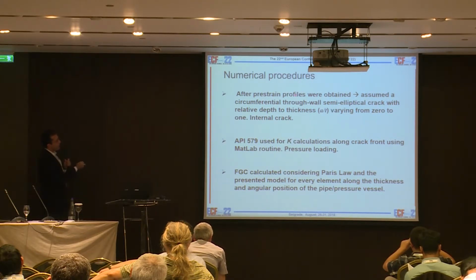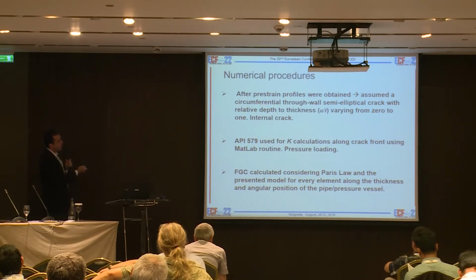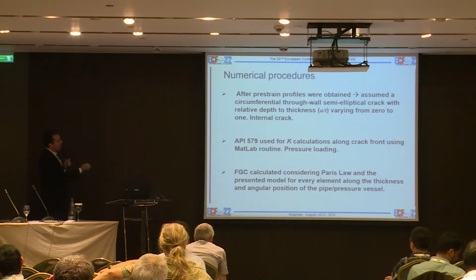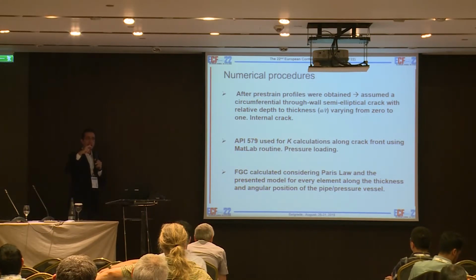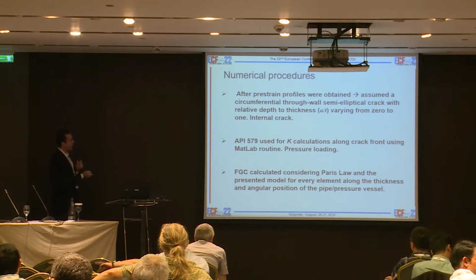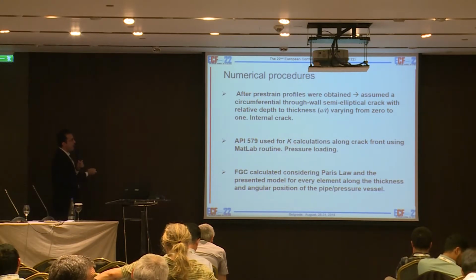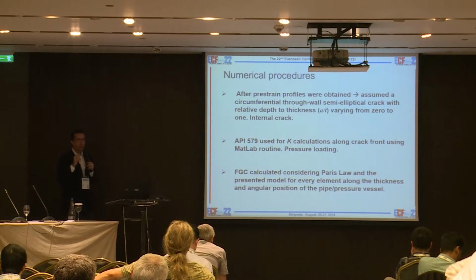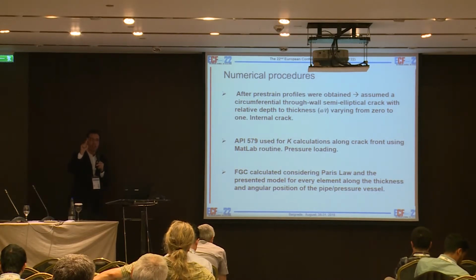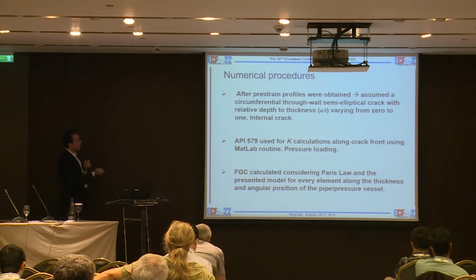After we simulated and got the pre-strain profiles, we assumed a circumferential through-wall semi-elliptical internal crack, with relative depth A/T ranging from 0 to 1. So the crack started inside and it grew until it reached the outside part of the pipe. API 579 was used for the K calculations, and a MATLAB routine was used to calculate K along the crack front. A fluctuating pressure loading was considered.